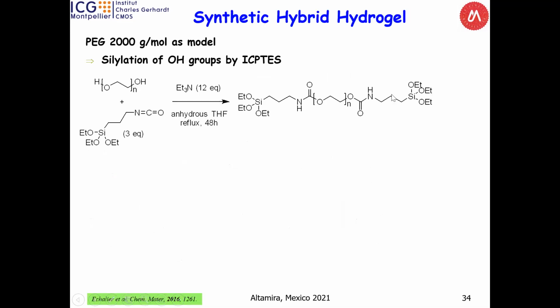So for the hydrogel, we started first with synthetic polymers. We took a PEG because it's highly soluble in water and biocompatible, and we silylated by the same strategy, attack of hydroxy oxygen on the isocyanate. We took isocyanatopropyl triethoxysilane under anhydrous conditions. Without any more details, it's enough. It's a very easy reaction. You can isolate it very well with high yield. And I will call it PEG 2SI, PEG for PEG and 2SI.